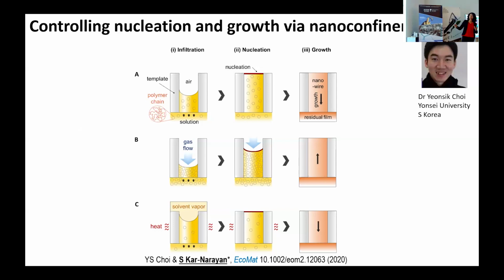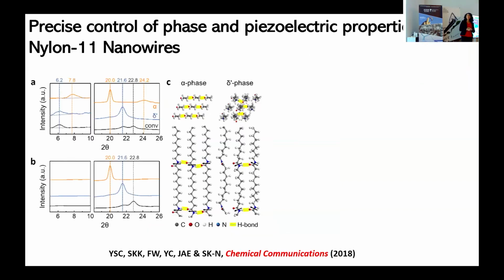So, the point of infiltration, the nucleation, and subsequently the growth of this material within these pores, and how we could manipulate this using various external parameters like the temperature of infiltration or gas flow or the controlled solidification process. All of this has been summarized in this nice review article here, so I won't go into detail. But the main point I want to make is that using these techniques, we can precisely control both the phase, which remember I said was important, and hence the piezoelectric properties in nylon 11.